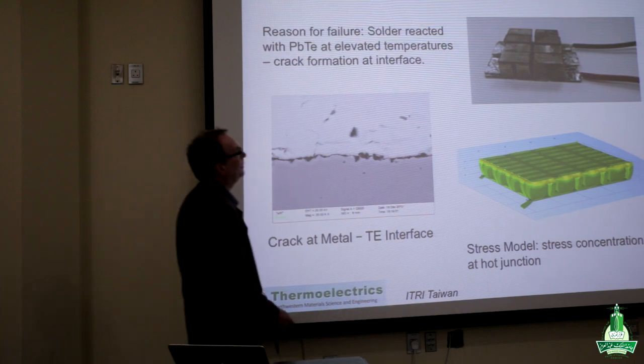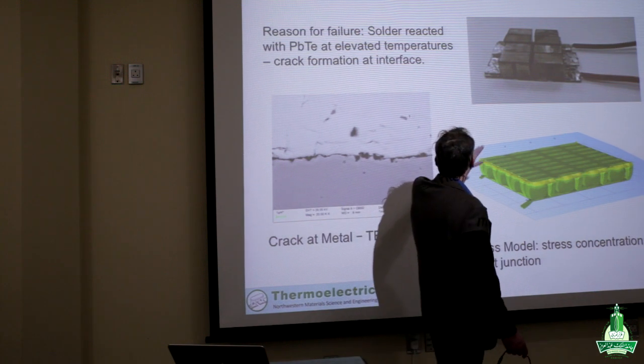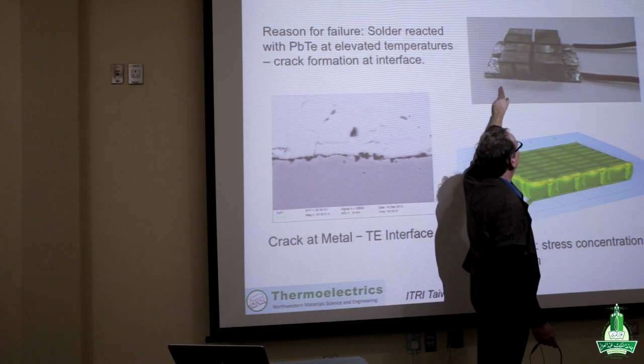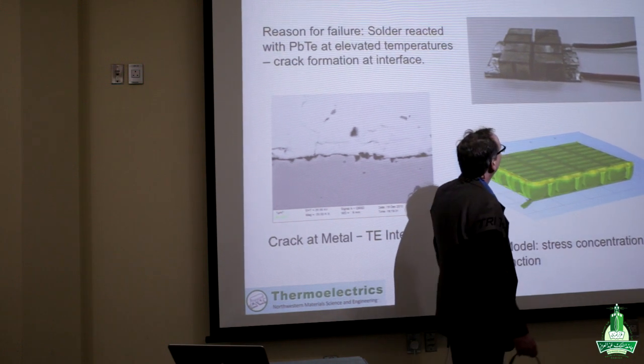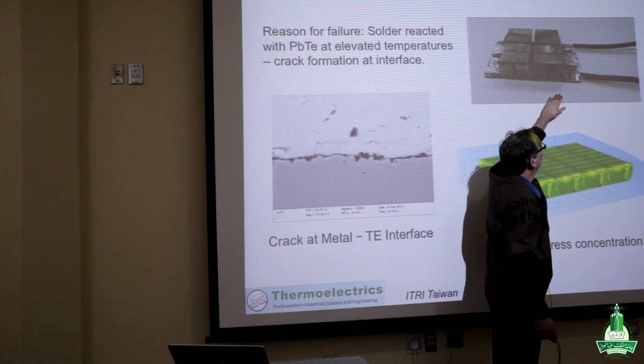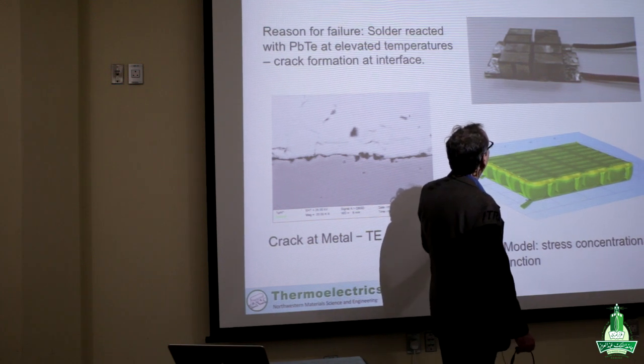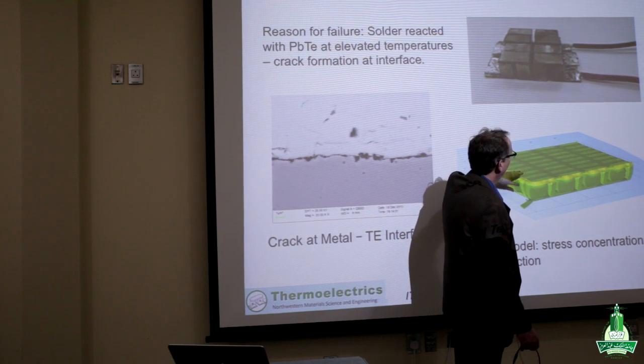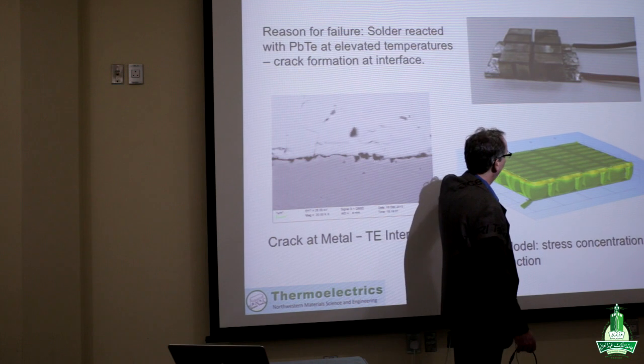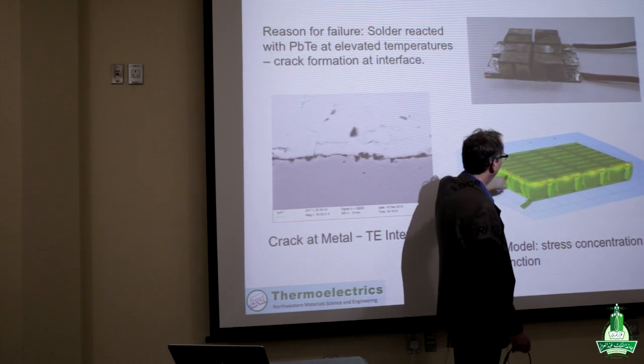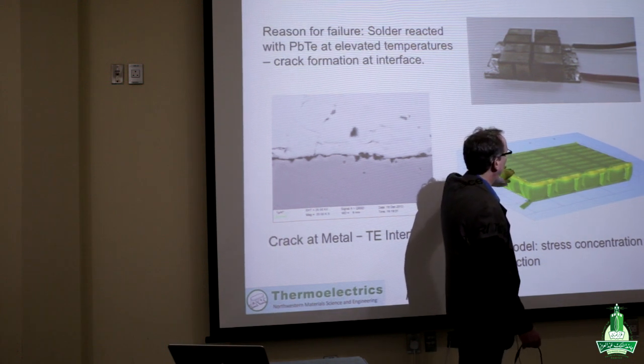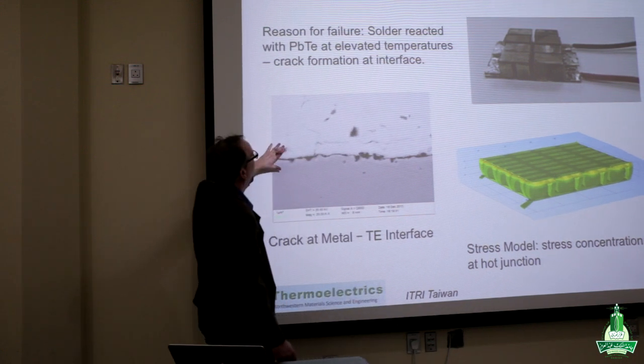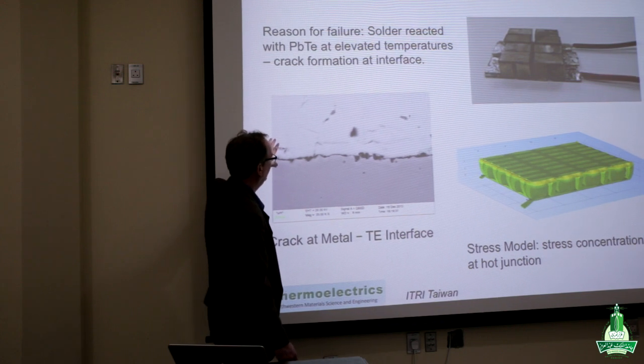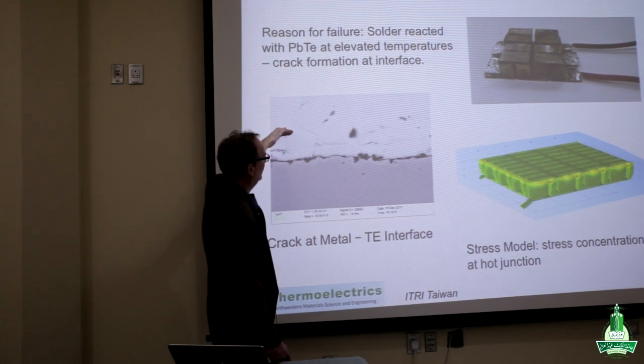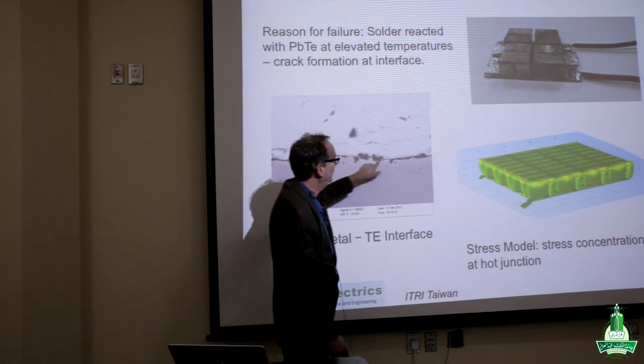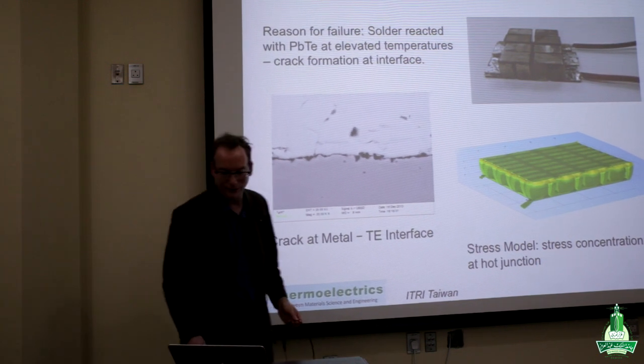Okay, so there are some other issues associated with these high temperature modules. We typically make a prototype module with n and p materials, and a hot side interconnect, and then all of that on top of a cold side substrate. And when we make these devices, there's typically a fabrication step that leads to very large stresses due to thermal expansion mismatches. Those stresses tend to be concentrated at the hot side of the module, and that leads to breaking at the interface. And here's an SEM picture of the hot electrical connect with the thermoelectric, and then a crack running through the material, which of course is going to lead to failure.